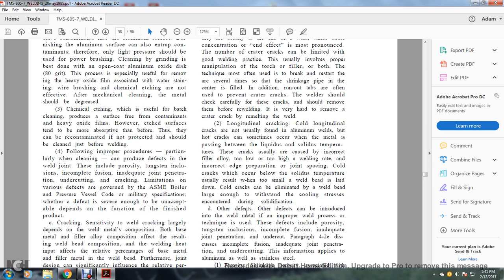Two, longitudinal cracking. Cold longitudinal cracks are not usually found with aluminum welds, but hot cracks sometimes occur when the metal is passing between liquidus and solidus temperatures. These cracks usually form because of an incorrect filler alloy, too low or too high a welding rate, and incorrect edge preparation or joint spacing. Cold cracks will occur below the solidus temperature. They usually result when too small a weld bead is laid down. Cold cracks should be eliminated with a weld bead large enough to withstand the cooling stress encountered during solidification.